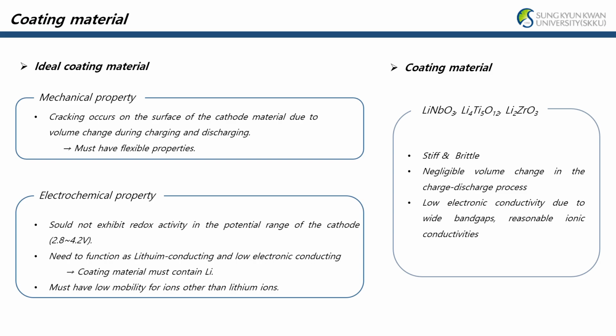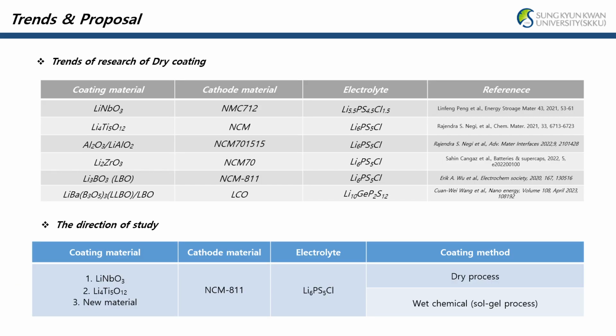They are relatively stiff and brittle, but they have a slight change in volume during charging and discharging, low electron conductivity, and reasonable ion conductivity. When NCM and NCA were used as cathode active materials in dry processes, materials such as LNO, LTO, LZO, and alumina were mainly used. Based on this, LNO, which is well-known so far, will be tested first, followed by LTO and new suitable coating materials.